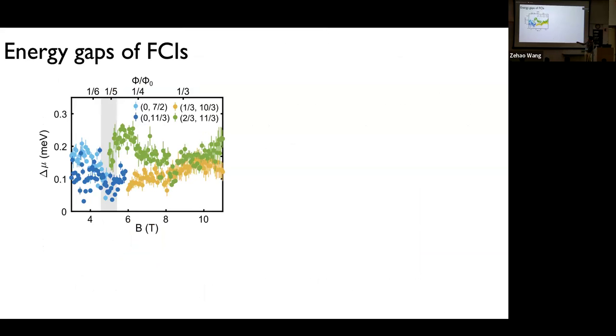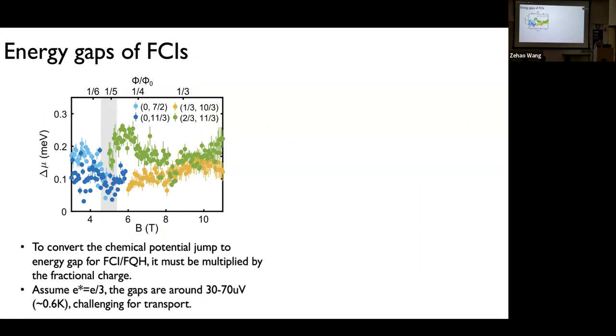and which is shown here for many of the states. And for the fractional states, basically are those that are marked in green and yellow or orange. And we can go ahead and characterize what's the number. You remember the prediction was 250 microvolt. And in practice, what we measure is here the change of chemical potential is around 150 microvolt. But there's a little subtlety here.